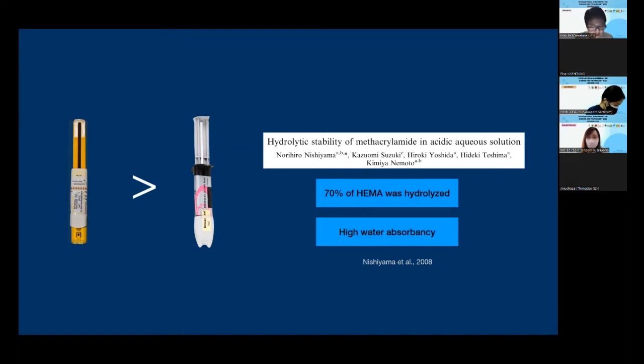This study found that Rely X U200 performed better in shear bond strength compared to Panavia SA Luting Multi. It could be that HEMA monomers in Panavia SA Luting Multi, which is hydrophilic, could lead to poor bonding. Dr. Nishiyama et al. showed that HEMA was hydrolyzed in aqueous acidic solution. Also, the high water absorbency of HEMA resulted in weak mechanical properties and poor bonding durability to the teeth.